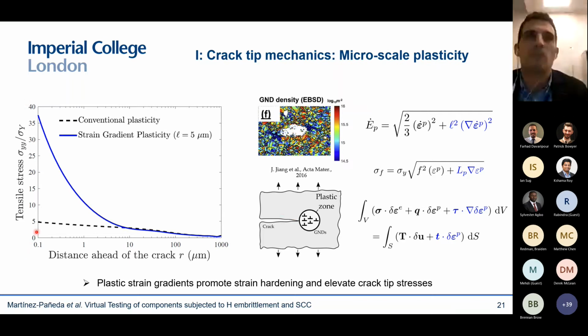And if you plot the tensile stresses ahead of a crack, this is the distance ahead of the crack, so here's the crack tip. What you see is that far away from the crack tip, those dislocation hardening mechanisms don't play a role, and you get the same results. But then as you approach the crack tip, and particularly when you are in this region where hydrogen-assisted fracture occurs, then you see that your stresses can be 2, 3, 4 times higher when you account for these dislocation hardening mechanisms. And that is important, of course, for 2 reasons, not only because failure would occur at a critical stress, but also because the amount of hydrogen that will accumulate will depend on the hydrostatic stress, as I mentioned before.